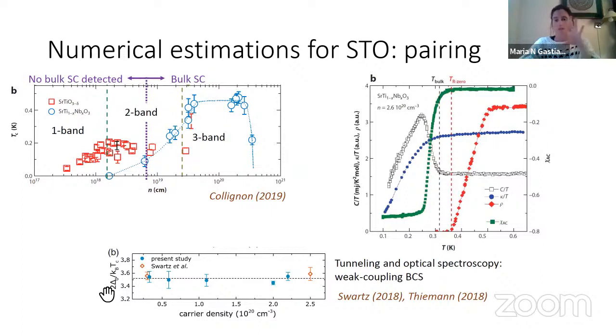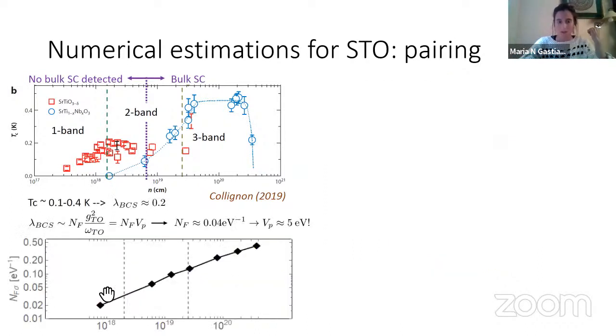So now that I've set up a little bit of the experimental background, something I think is pretty remarkable in this material is this: if you have a TC of around 0.1 to 0.4 Kelvin, we know it's weak coupling, and then you extract from TC proportional to the exponent of -1 over lambda. What kind of lambda should you get? That is of the order of, let's say, 0.2, which is within weak coupling.